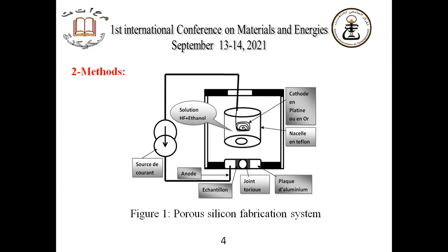the series of porosilicon samples were prepared using P-type silicon substrate. The electrochemical cell presented in Figure 1 was made of Teflon, while the base plate was made of aluminium. The silicon wafer was mounted as the base plate, making a ring of silicon surface, which was exposed to the electrolyte. The porosilicon layers were performed using a controlled electrochemical etching method.